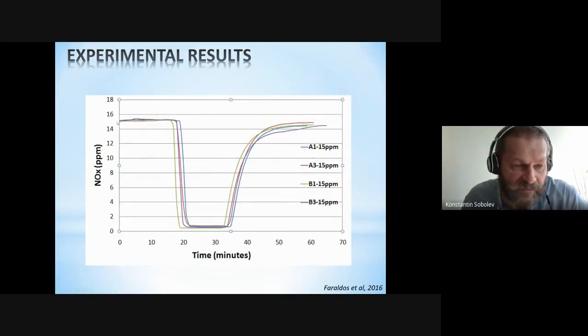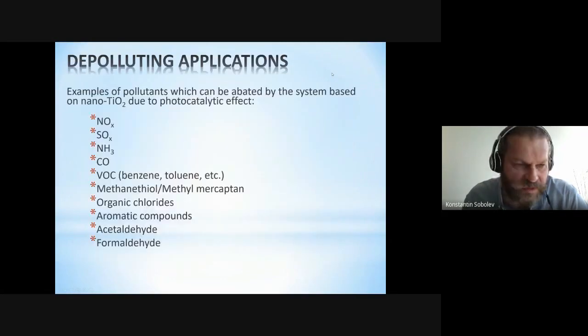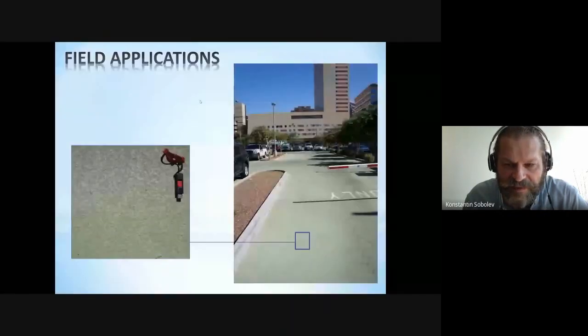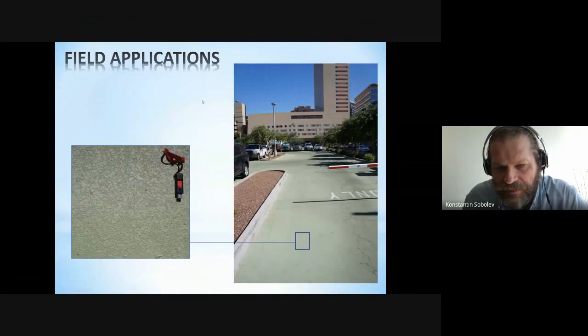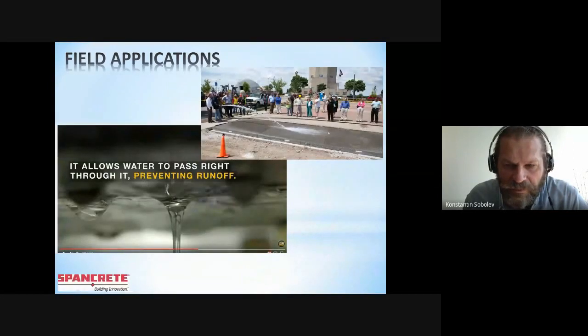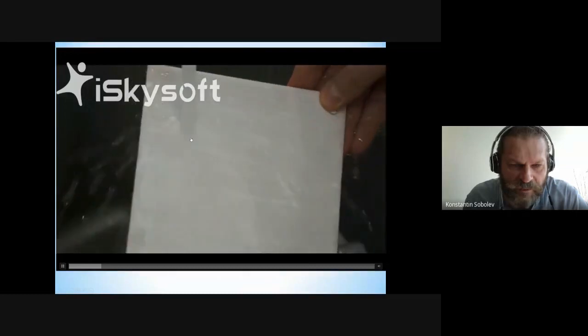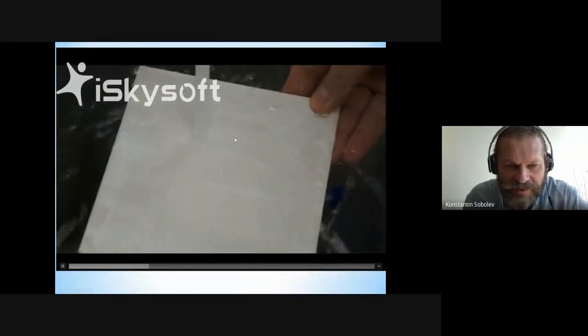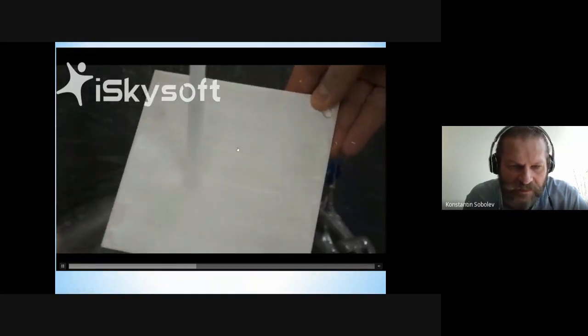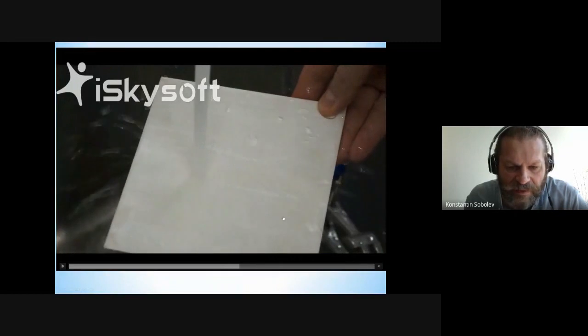The compositions are very effective at 15 ppm as well, an extremely high concentration, more like industrial gas, and can be used for other depolluting applications. This is an example where a similar coating was applied in Arizona. After a number of years, it was still performing well. A project we had involved photocatalytic concrete and pervious concrete in combination. Here is an example of photocatalytic and superhydrophobic coatings, which can be easily combined. You can see a ceramic tile coated. This would be wet. It's dry, remains dry, and you can see the droplets there.